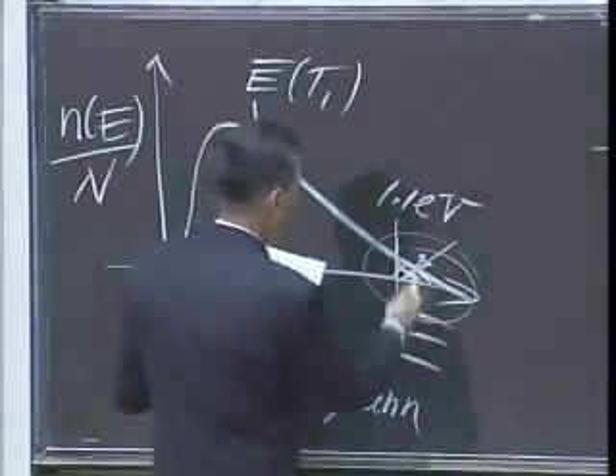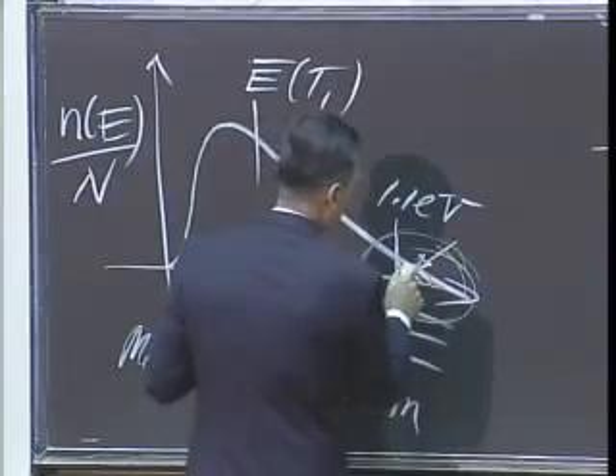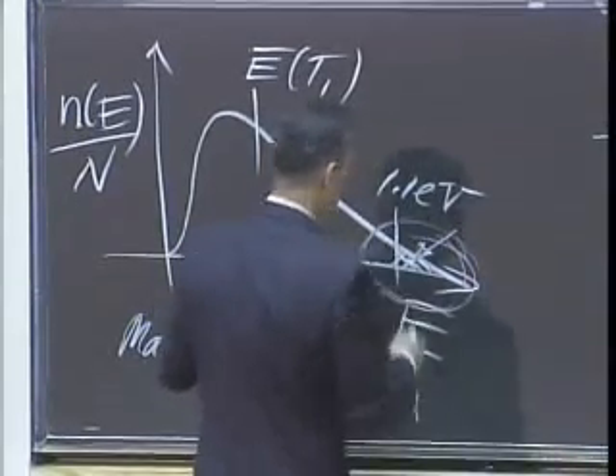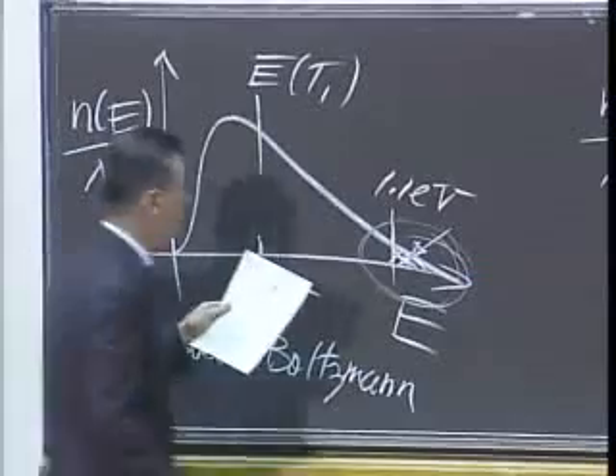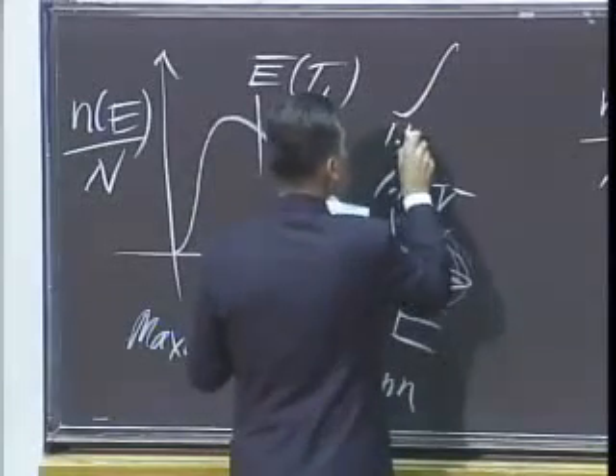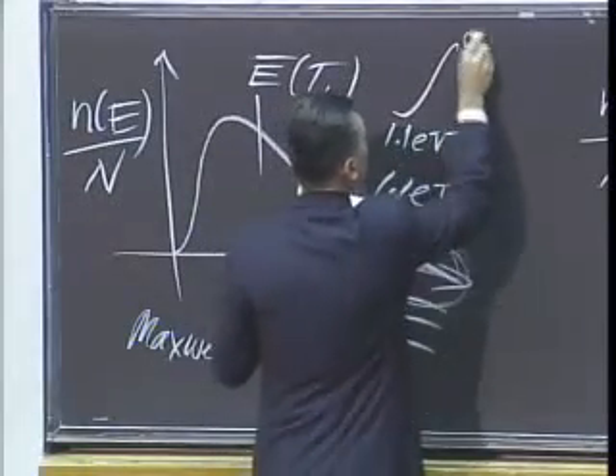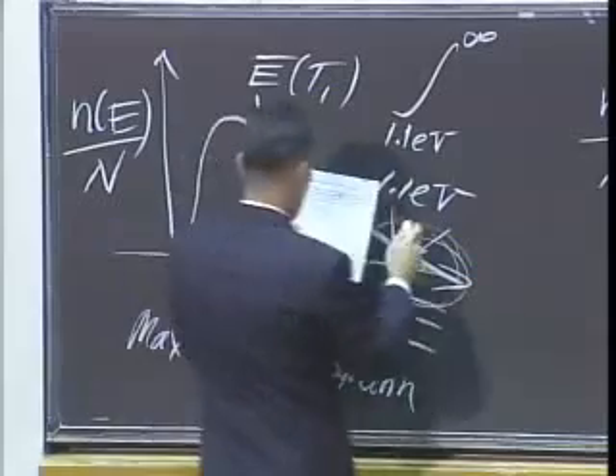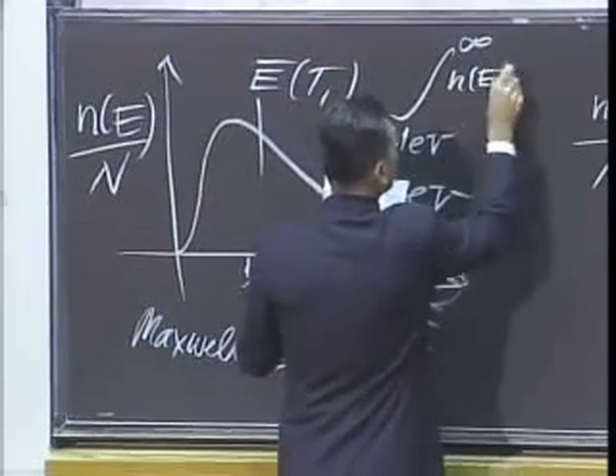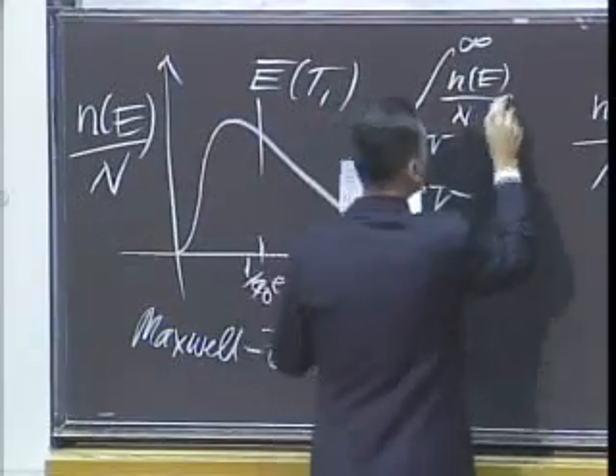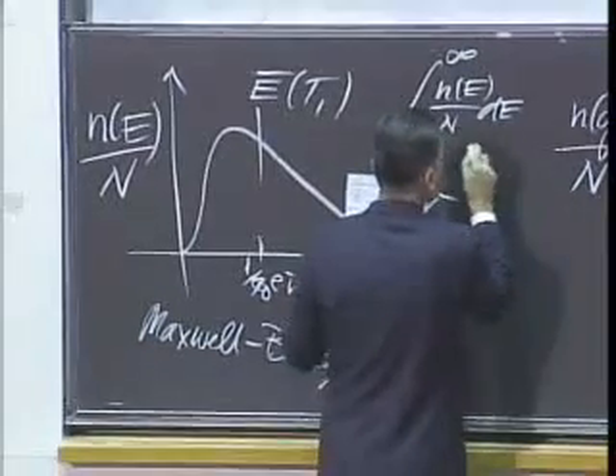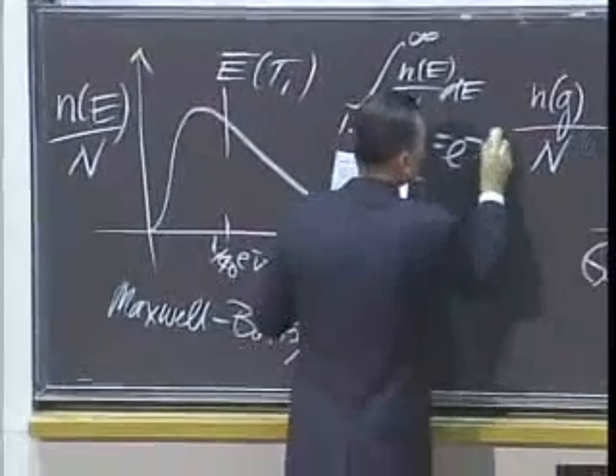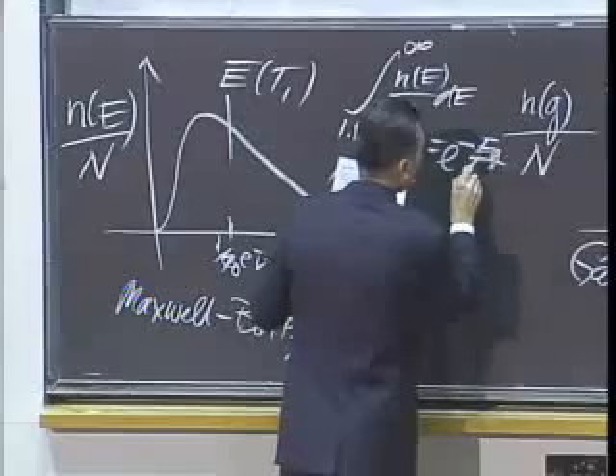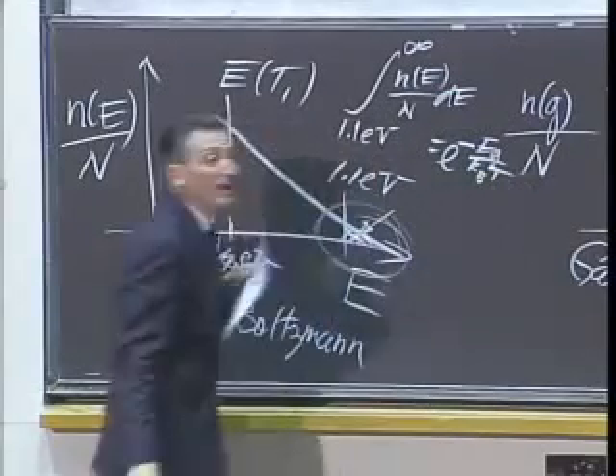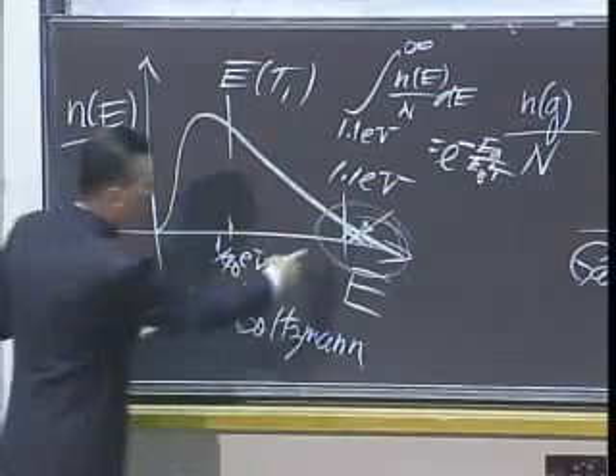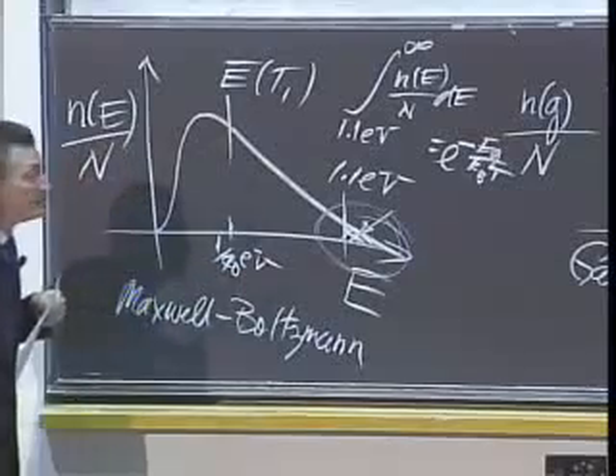There's a tiny value out here. And the nature of this curve is that the fraction of the distribution out here, if I integrate from 1.1 eV out to infinity, is the area under this line. What am I integrating? I'm integrating the fraction times dE. This equals e to the minus energy gap divided by k Boltzmann times temperature, this exponential. That's what gives us the fraction underneath this line.